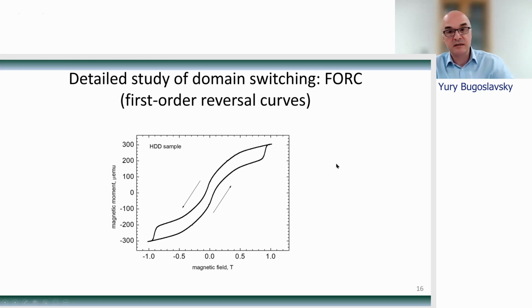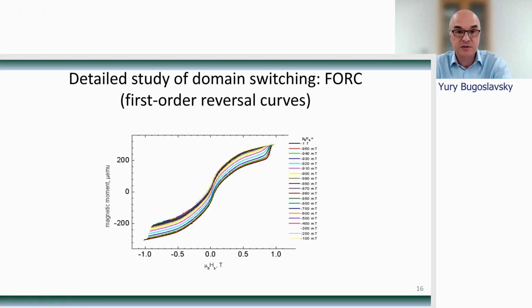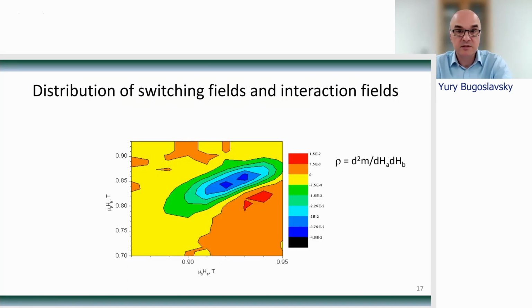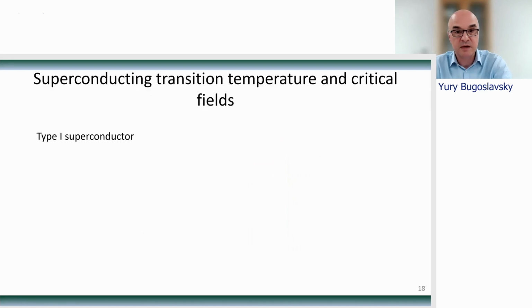We can study the reversal, the switching of the magnetic domains in the ferromagnet, in more detail by employing the beautiful technique called first order reversal curves, which records partial hysteresis loops starting from different values of negative magnetic field. And here we usefully employ the automatic aspect of our machine, so we can run repeated measurements automatically, varying some parameters and producing a bunch of nice looking curves. They can be processed further to produce a colorful picture which describes the distribution of interaction fields and switching fields in this ferromagnet.